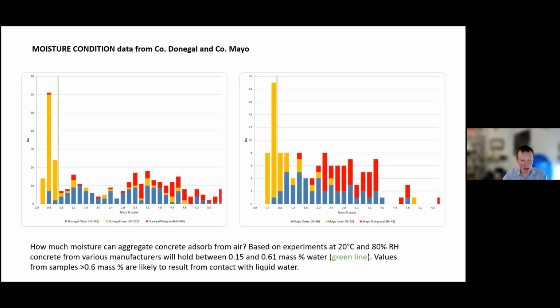And this data is 472 determinations from individual cores that I looked at. On the left, we have cores from Donegal, and on the right from County Mayo. And these are histograms which show the mass percent water on the horizontal axis, and the number of cases on the vertical axis. Now, the interesting thing is that if you take concrete and you leave it to equilibrate with moisture in atmospheric air, you will probably end up with an amount of water between 0.15 and 0.61 mass percent. So I've put this on each graph as a vertical green line. So if the concrete was just left dry and not in contact with liquid water, that's where you'd see it. So everything to the right of that is in contact with liquid water.